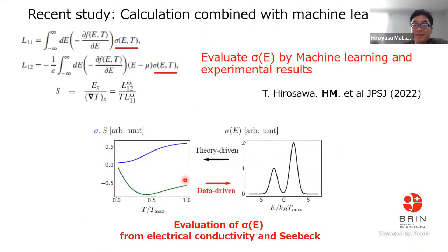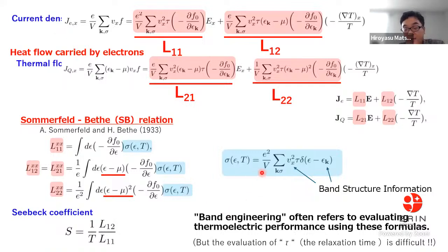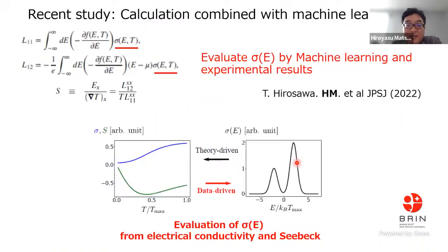Recently, when we calculate this sigma, we need tau, but band calculation does not give tau directly. But recently we made a new method to obtain this sigma from experimental results, by machine learning and experimental results. The schematic picture is like this. Usually we use this equation to calculate sigma with a band calculation, and then we get L11 and finally the electrical conductivity.